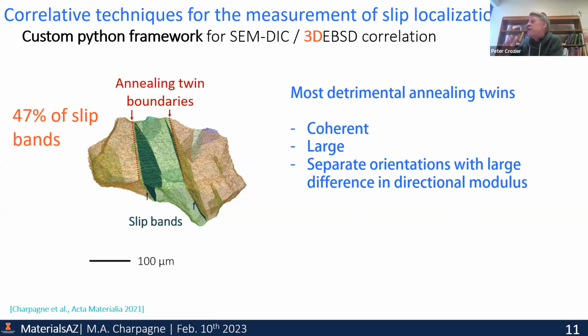They shear and then they sort of shear back again, but it seems that it's the strain that builds up because of the adsorbates on the surface that temporarily relaxes through the formation of a twin, but we're struggling to understand the mechanisms in detail. So it's just very interesting that you're having this twin boundary and it's somehow causing the formation of a slip plane some distance away.